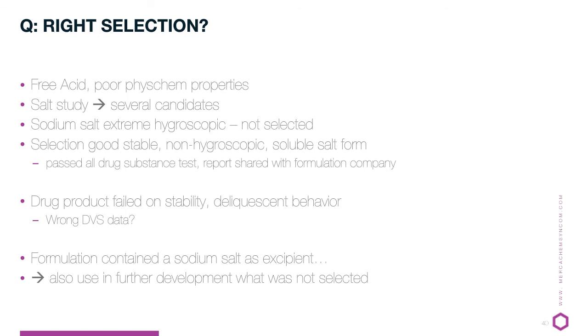The question we got was, did you get the right studies? Did you do the hygroscopicity study on this material as well? We knew that this salt was not hygroscopic, not at all. We had a look at the formulation, and there we saw that one of the excipients was a sodium salt. Making the formulation allowed to change the salt form into the sodium salt, which was extremely hygroscopic. So again, knowing what actually your formulation will be would have avoided this one.